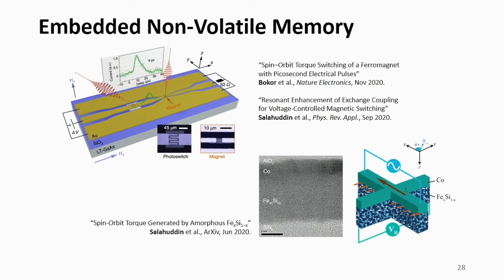So just a couple of examples here. We would like to have embedded non-volatile memory devices integrated for very ultra energy efficient mobile computing and Internet of Things devices. So the Bokor and Salahuddin groups are developing current-driven magnetic devices. So rather than using a magnet to switch the magnetization of a nanoscale magnetic material, we can use current to actually flip the magnetization. So the interesting thing of the upper plot is this waveform, this green pulse. We've shown that a nanomagnet can switch its magnetization within 6 picoseconds with a pulse of electrical current.